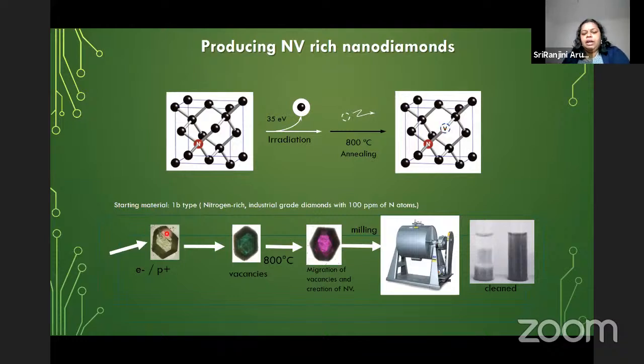So basically you take the diamond, create the vacancies, and migrate the vacancies at 800 degrees. When it is cooled, it is followed by putting it in a ball milling machine. This is a very, very small nano-sized diamond, less than 10 nanometers in size. They are kind of blackish soot, a blackish color suspended in ultrapure water.